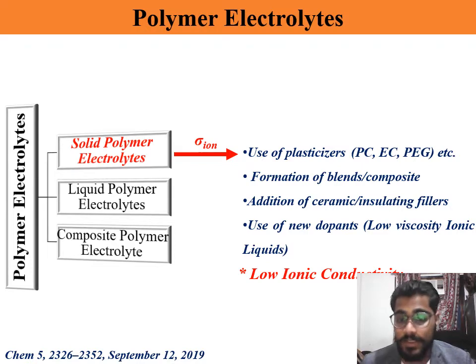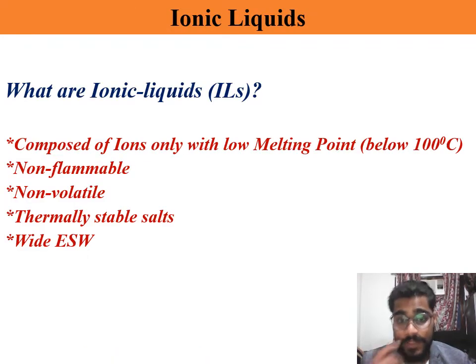For the synthesis of these SPE, we use different plasticizers, we form different blends, composites, addition of ceramic insulating fillers, use of new dopants, and low viscosity ionic liquids. It has very few disadvantages, the main one being low ionic conductivity. But because of the freestanding film of this SPE, we consider it to be the best for the stability of our electrochemical devices. Next, we have the ionic liquids.